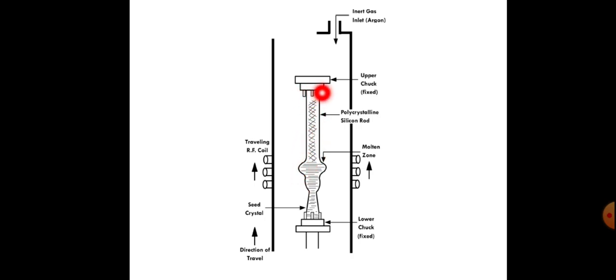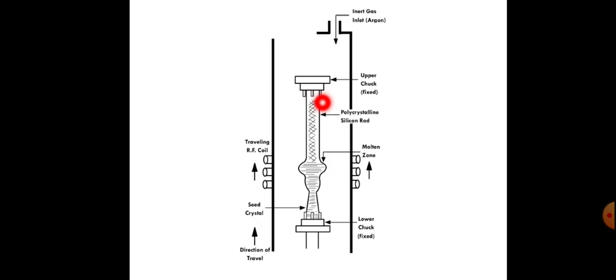After the process, we can cut that impure top part away, and we will get a pure crystalline silicon rod without impurities. This process can be repeated in order to get highly purified single crystalline silicon. We heat from the bottom again and move upward so all impurities are collected at the top, and that impure portion is cut away using the appropriate saw — which we will discuss in later wafer preparation sessions.